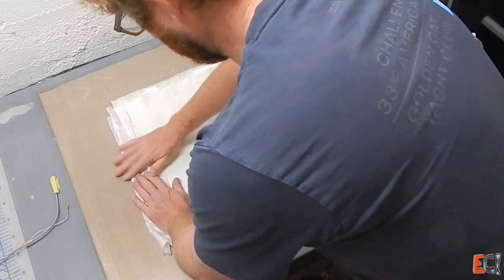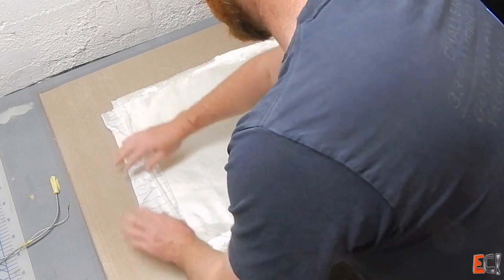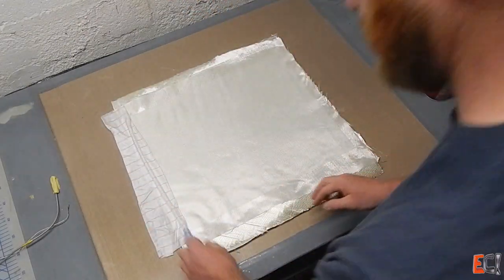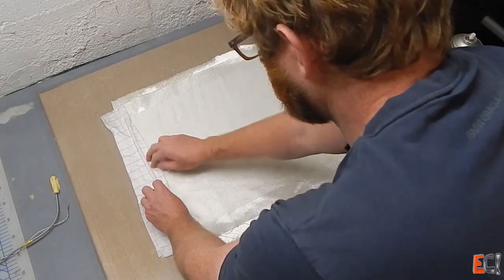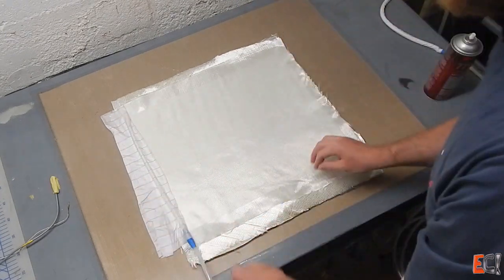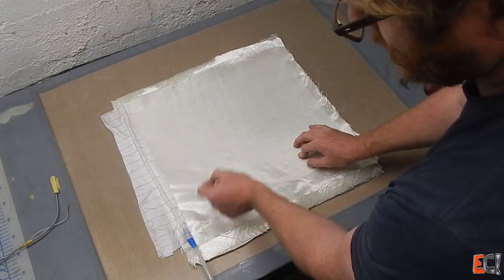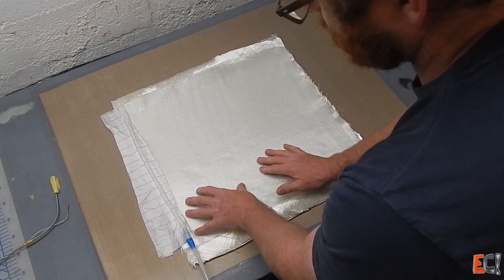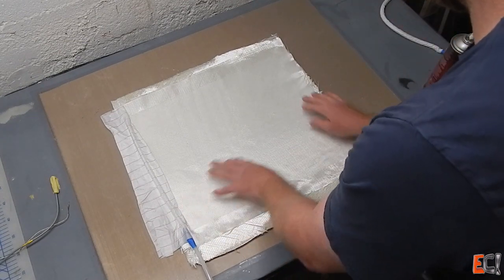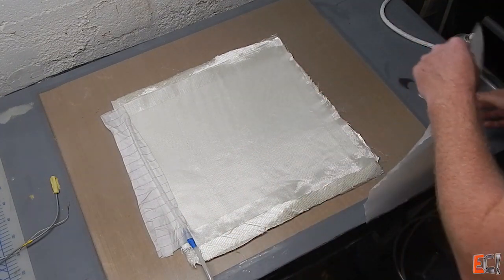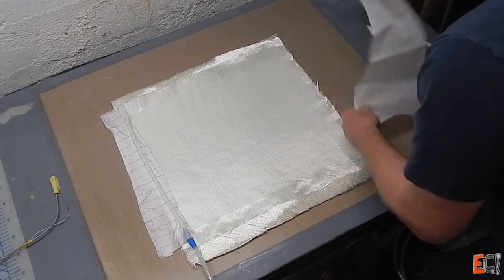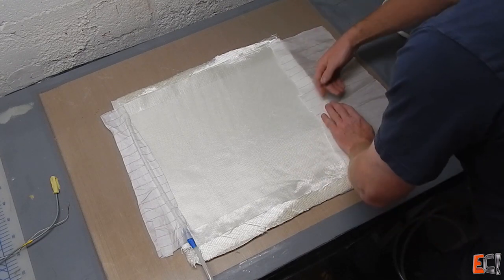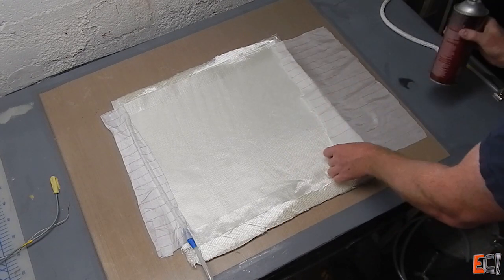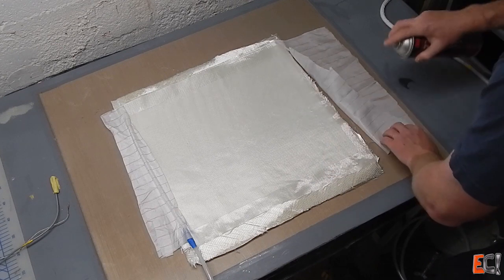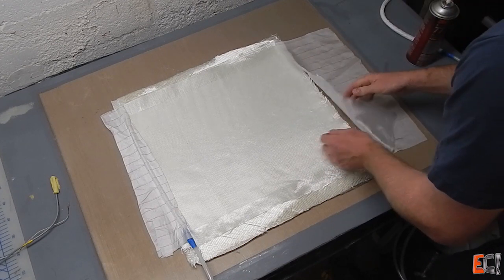This is a ProSet infusion resin, and the resin itself in the bucket is relatively cool, but this table surface, the mold surface, is going to be quite warm. This is up around 100 F, and so it's warm to the touch, and that will really drop the resin viscosity as it hits the laminate stack and will sort of optimize for permeability. Lower viscosity resin will flow better through the fibers.